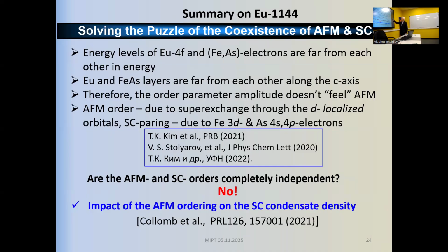But in fact, much later, when we put in some numbers, we understood that the antiferromagnetic ordering, which is not possible only due to direct dipole interaction of europium atoms, mainly occurs due to super exchange interaction, not by RKKY, but through the localized orbitals of iron and arsenic, which are the most effective. RKKY, by the way, curiously has an opposite sign. It oscillates as a function of distance, but for this particular distance, it produces a weak ferromagnetic effect. So it is negligible on the background of the super exchange interaction.